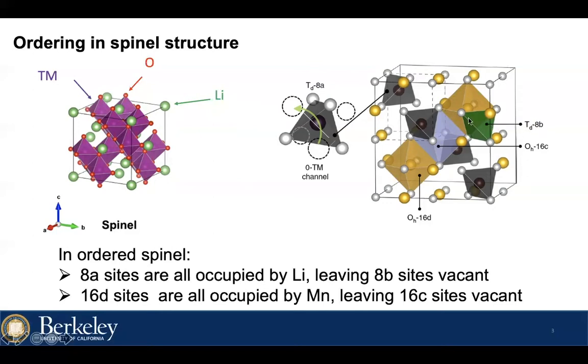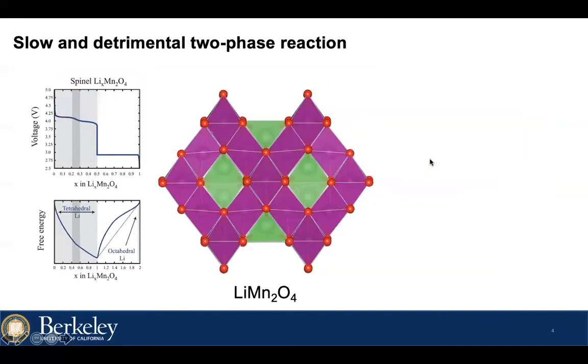And for the lithium, all the lithium sits in the 8a site, and they face-share with a vacant octahedral site called the 16c site. So lithium is migrating from one 8a site to another through this vacant octahedral site. Due to the low migration barrier and 3D migration network, the spinel structure is very favorable for lithium transport. However, this spinel structure cannot do fast charging. Even at low rate, it cannot deliver high capacity.